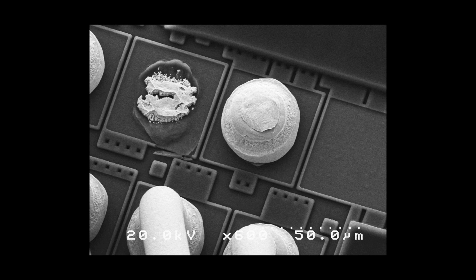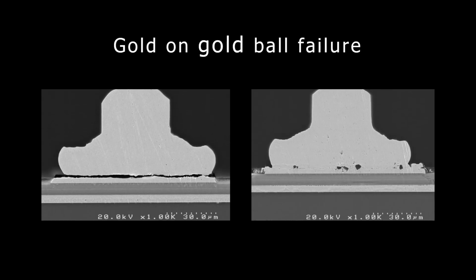Sometimes it is possible to see cratering-induced defects by pulling the bond wires. The left pad has deformation and cracking, and possibly cratering. The right pad shows how a healthy bond wire should fail in pulling, by breaking at the neck. These are two examples of failed parts. The left bond wire is completely severed. The right is partially separated.